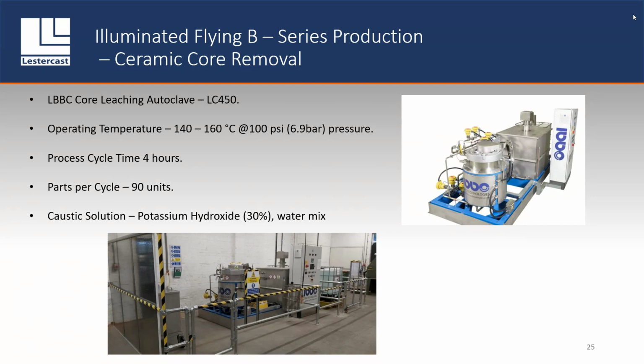So working with LBBC and Bentley at the time, Leeds and Bradford Boiler Company, who supply us with the boiler clave. I think they're the world leaders in that sense. So most investment casting foundries around the world will have an LBBC boiler clave, but they designed this, which is a core leaching machine. Effectively, we put the parts into a basket in a configuration up to 90 parts per cycle, and over the time of around about 4 hours, it goes through a washing process.